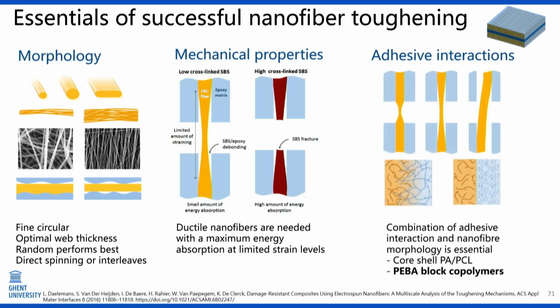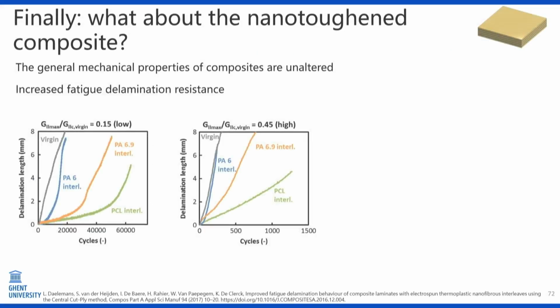Now, core shell is a bit less easy to produce than just conventional electrospinning, and that's why we then, in our later work, moved to commercial PEBA block copolymers, which combined both the retainment of the fiber morphology and the adhesive interaction all the way through the processing of the polymer. So now that we've developed that platform, are they really of use in true composite materials?